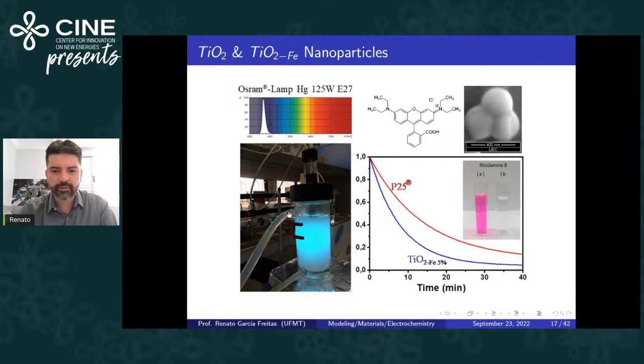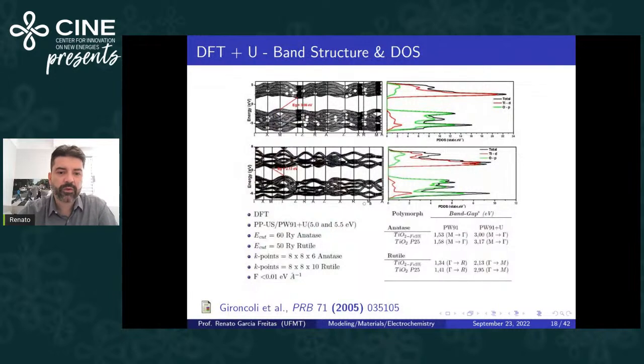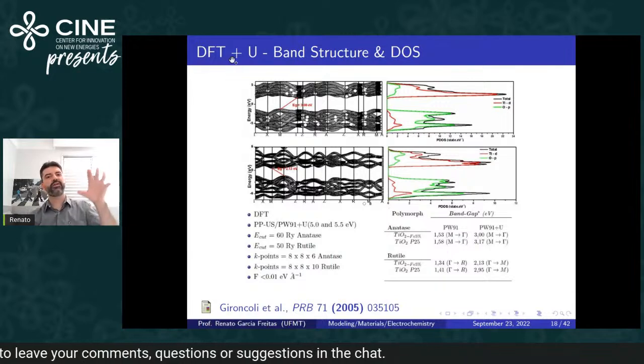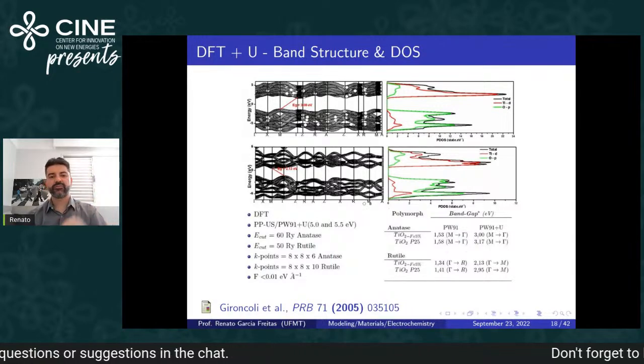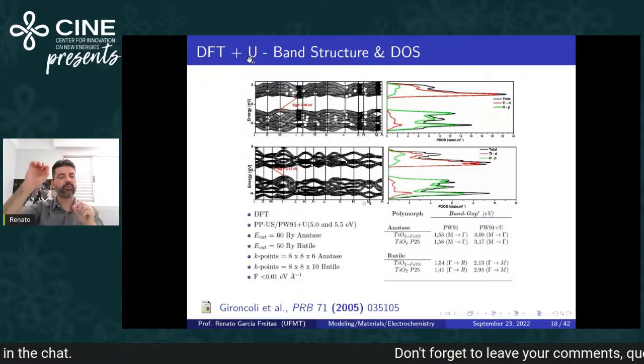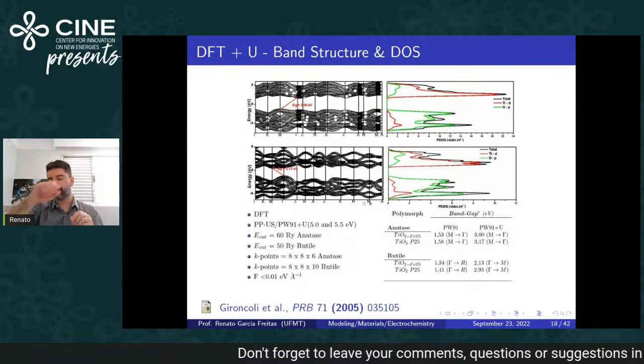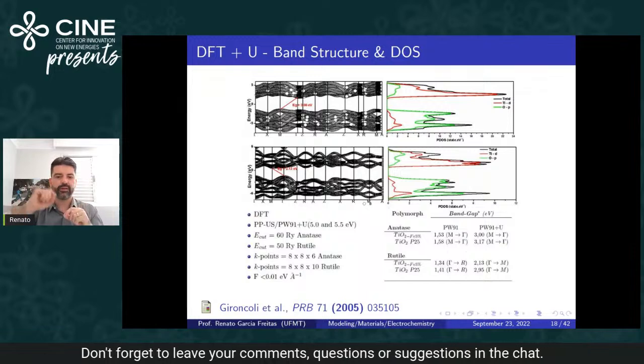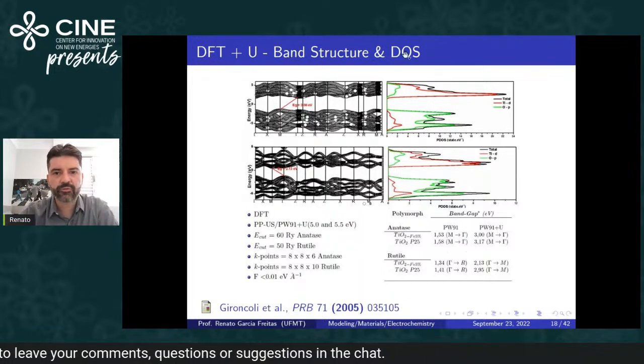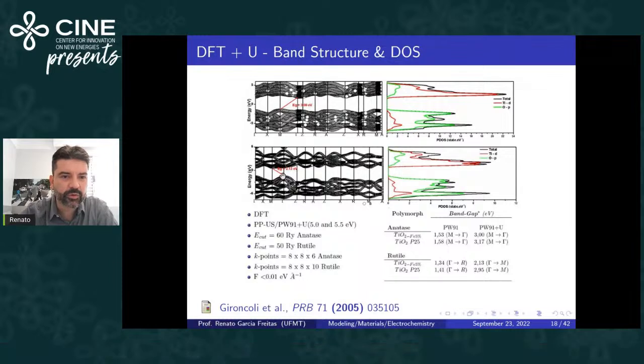In this part, so the reactor here, and what you can do with this kind of thing, they have the X-ray diffraction. We performed the Rietveld refinement as well, and we did some electronic structure using Quantum Espresso. So in this case, remember, coupled cluster, DFT, but DFT in this case we use the Hubbard correction, because we have the problem already known from density functional theory, that it underestimates the band gap values. And the band structure and density of states in this case, we have from anatase, rutile, the M gamma indirect transition, band gap 3 electron volts. In this case, we have gamma M 2.1 electron volts.